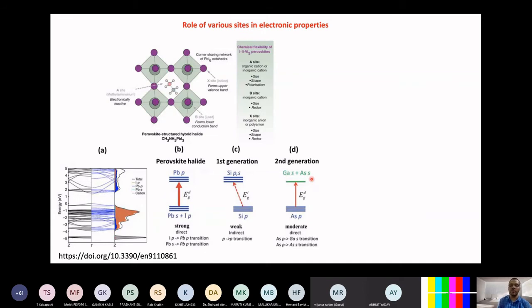However, perovskite things are different. You have got your charge carrier hot in the conduction band. However, instead of s orbital, it's a p orbital. So it somehow restricts electron motion. And moreover, your valence band has got s character as well. And that makes your whole hole mobility slightly better with respect to your electron mobility. And hence, the perovskite is the only semiconductor where you find ambipolar character. Ambipolar means you have got electron and hole mobility almost the same for a given semiconductor, which is happening because the effective masses are the same.